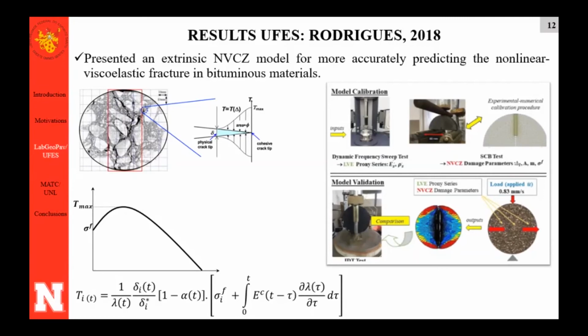She did a DSR test to obtain linear viscoelastic properties. She did an SCB test to do an experimental numerical calibration procedure and get the nonlinear viscoelastic cohesion damage parameters. And with the nonlinear viscoelastic cohesion parameters and linear viscoelastic parameters, she could use those as input to validate the mixture performance in another test.